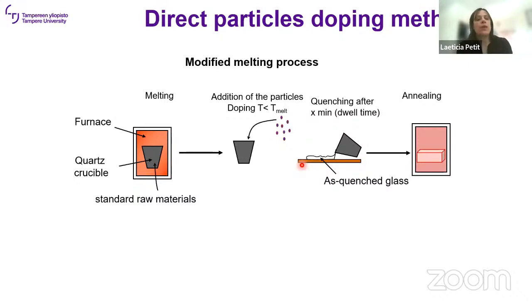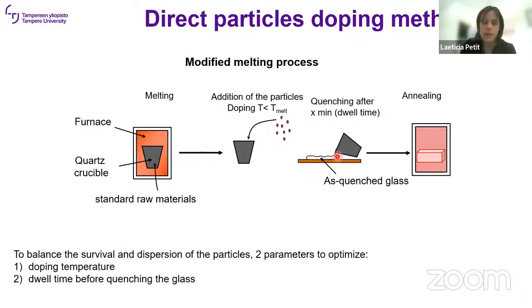As I said, we are also working with a direct doping method. So we prepare crystal, and then we add the crystal in the glass. So you have the process of the glass melting here. We melt the glass, then we add the crystal at a specific temperature, and then we quench the glass, and then we anneal. So in this process, we need to balance the survival and the dispersion of the particles.